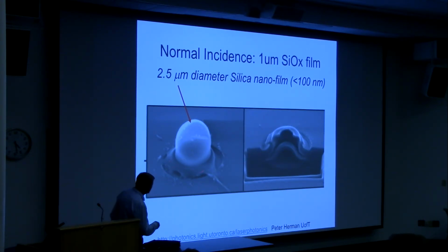Here's ion milling of this structure. You can see that multiple layers, multiple disks have exploded. They're competing with each other in explosion. Some disks are flying completely off. Others form these incredibly thin bubbles. This is pure silica, probably like 150 nanometers thick. It's enclosing a zone that might be vacuum. You can see the peeled layers like a burst bubblegum spread here. And inside are voids. The morphology is really cool.